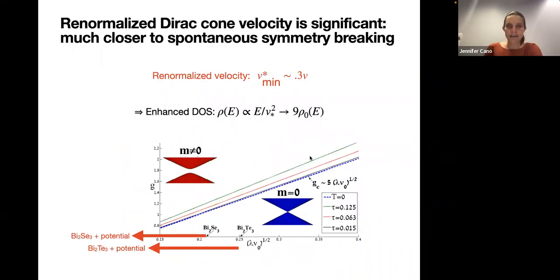I want to emphasize that this is actually a pretty big change, because if the velocity goes down by a factor of 3, then the density of states, which goes like 1 over velocity squared, will go up by almost a factor of 10. That's a non-trivial change. And if we return to this plot that I was showing before, remember this is interaction versus square root of velocity. This is showing us the critical interaction strength needed to gap the Dirac cone. If we change velocity by a factor of 3, this pushes bismuth selenide and bismuth telluride way over. And it looks, in fact, like bismuth selenide might be above the critical interaction strength predicted by this calculation. So this renormalization by a factor of 3 might be enough to realize a gapped magnetic surface state.